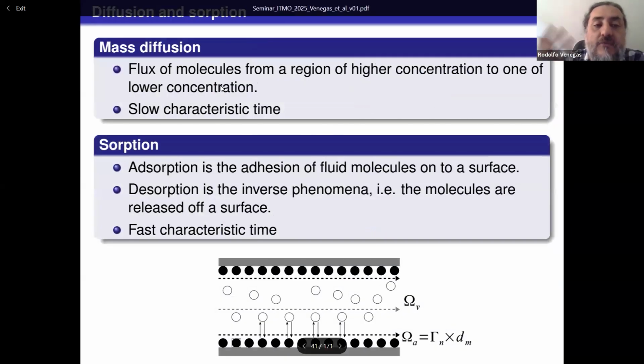So first, mass diffusion, just to remind, is a flux of molecules from a region of higher concentration to one of lower concentration, and generally has a slow characteristic time in comparison with what happens at sorption. Sorption is a term that we use to denominate adsorption and desorption. So adsorption is the adhesion of fluid molecules onto the surface, as we can see here with these black circles. Desorption is the inverse phenomenon. So these molecules get released off the surface and are in the bulk of these small pores, as shown in these white circles here. And this has a fast characteristic time. So the residence time of these molecules on this surface is pretty small.